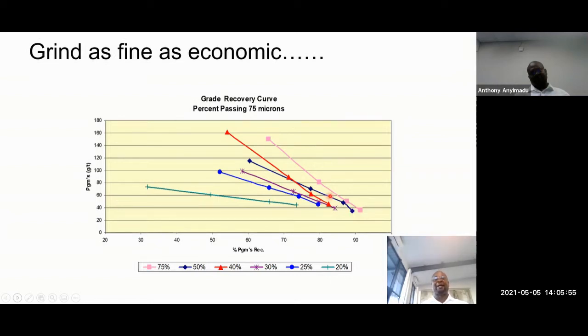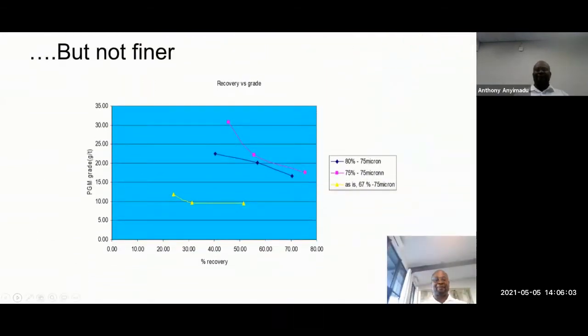But the second part of the statement I've made is, but not finer. So when you go to the next one, if you try and push your luck too much, this was the 75% passing 75 micron that you saw. As soon as we got to 80, we go back. So not only are you wasting energy, you are actually going to a lower technical performance. Again, we know the end shape: too fine, not good, too coarse, not good. But we will use these to discuss exactly what it means. The reason this is important is because many people think a little bit, 5, 10% up or down, doesn't really matter, but I think it does.